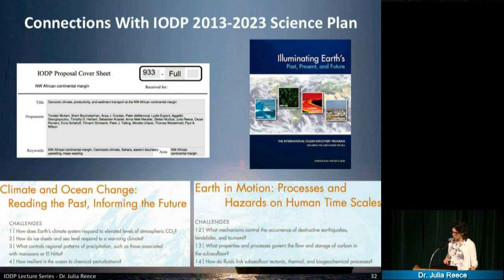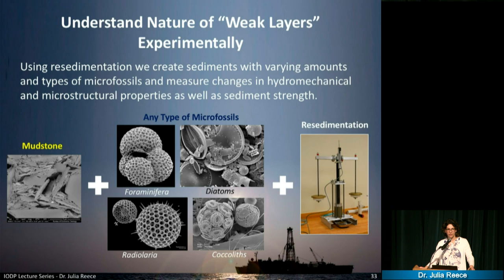And so what I think would be great to do is use this resedimentation technique to mix in microfossils with mud in different fractions and then compress it and see at what stress they start to break, which might release a lot of fluid and can then cause the sediments to fail, but also to understand what concentration of microfossils is important to actually change the behavior. And so that's what I plan to do, mixing the mud with different microfossils, not only diatoms, but we can also use foraminifera or coccoliths or radiolaria, and then test the behavior in the laboratory under controlled conditions.